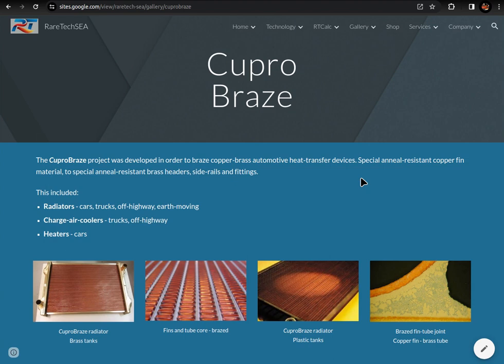So what Outokumpu did is they developed an anneal-resistant copper fin. They put in a certain ingredient, which what would then happen is as you move through the brazing process, this ingredient would move around inside the copper, and then it would actually strengthen and stiffen the copper. In fact, it was so stiff after brazing you could actually make it ping. It would sound like a little bell. It was actually quite amazing.